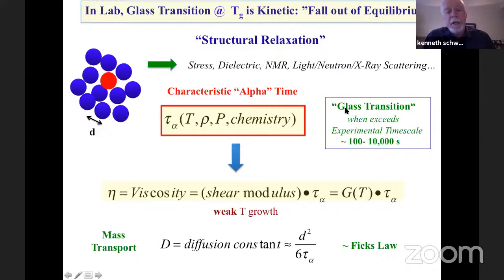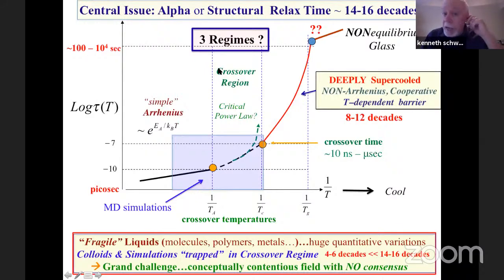So from the practical point of view, the glass transition is when you fall out of equilibrium, which is when this time scale exceeds the experimental time scale, which is of the order of 100 to 10,000 seconds in a typical experiment. And if you want to understand how the viscosity changes or the diffusion constant changes, yes, they're not the same properties, but to 0th order, the alpha time also controls their spectacular changes with things like temperature. So here's my key plot that really the talk revolves around. What I view as still the central problem is to understand this relaxation map of structural relaxation that can span 14 to 16 orders of magnitude in equilibrium. So what's plotted in a schematic way is the log of the alpha relaxation time versus inverse temperature, going from picoseconds to 100 to 10,000 seconds.